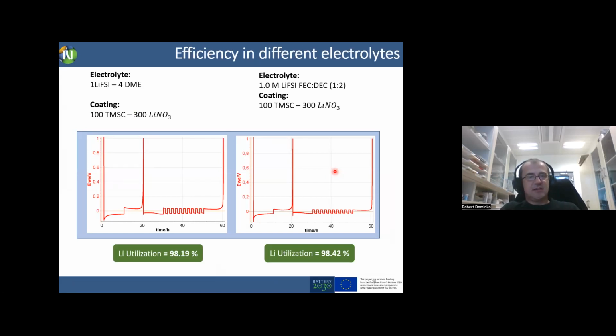So recently we are studying this more deeply in different combinations of electrolytes, and I will also show different combinations of salts. And we are using a methodology of using 1 milliamp hour current and 10 hours charge deposition, stripping and deposition. And then we deposit again or strip again, and then we do short cycles, and then we check how much lithium remained here. Those are efficiencies. Of course, this is a different procedure compared to the literature, but for us, this methodology was established, and we are comparing this efficiency.